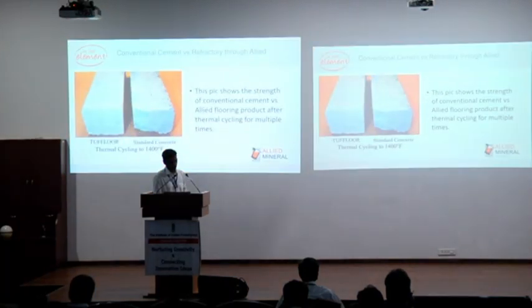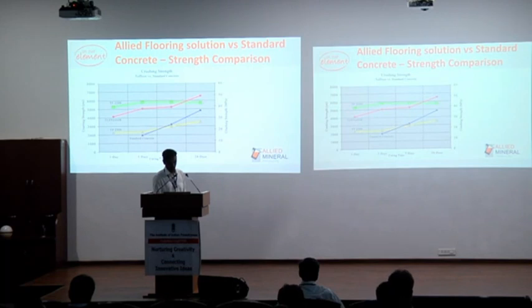This is a picture which compares Tough Floor versus standard concrete after multiple thermal cycling at 1400 degrees F. You can see the standard concrete does not hold up as well as Tough Floor. Tough Floor has the high strength to hold that kind of atmosphere. This graph shows the strength of Tough Floor with respect to the standard concrete. The blue line represents the standard concrete, and the others are different grades of Tough Floor, and the strength they attain with respect to curing time, in terms of crushing strength.